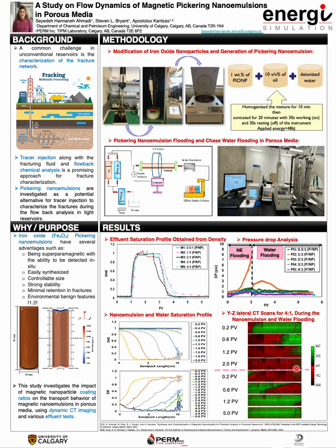As we interpret the CT images, the green color represents water and the red color represents nanoemulsion, and this is the channeling of water when we inject water in the sandpack. So as a result, we can say that by increasing the coating ratio, the stability of the nanoemulsion increases, and it can move through the sandpack very easily, and we can recover all the nanoparticles and nanodroplets that we inject into the sandpack.